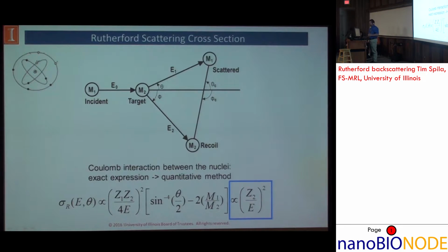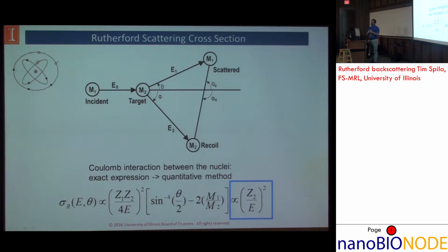What's also nice is that because we have a Coulombic interaction between the nuclei, we can determine an exact expression for the backscattering. Thus we can say that RBS is a quantitative method. It's a fully quantitative method. And we can define a scattering cross-section, that's this right here, as a function of energy and angle, which ends up being proportional to the atomic number divided by the energy quantity squared.